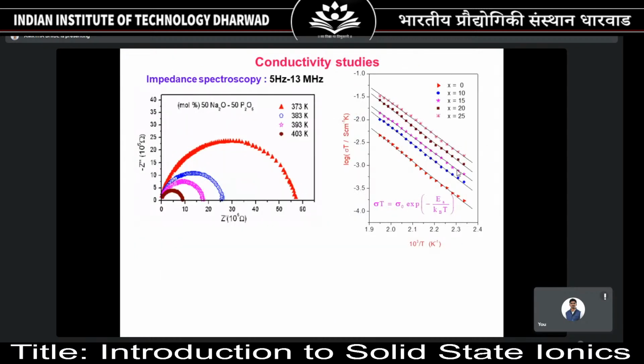As I told, these materials being ionically conducting, you cannot use the typical DC conductivity measurements. One has to go for impedance spectroscopy. Otherwise, if you go for DC conductivity, the electrolyte gets polarized and you won't be measuring any ionic conductivity. You are simply measuring an apparent resistance or electronic conductivity. As I told, as you keep on increasing the temperature from 373 Kelvin to 403 K, the resistance decreases. If you consider the real part of impedance, it is roughly 100 kilo ohms, whereas at a lower temperature, about 150 degrees Celsius, it is about 60 kilo ohms. So this is how the conductivity changes, and it is well reflected here.